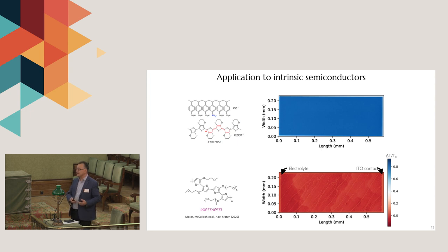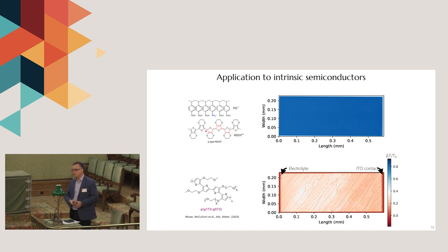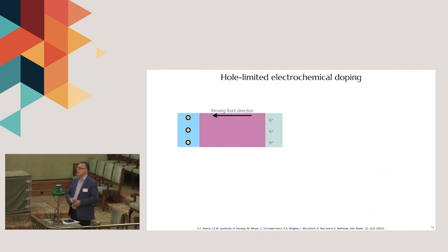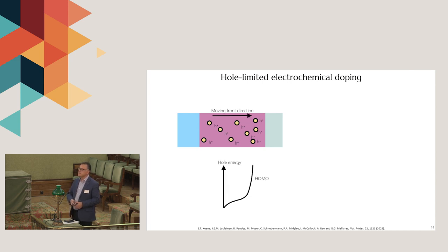This is an undoped polymer that gets doped through injection of anions and holes. And if you see here, the behavior is more complex. You have a front that starts from the left to the right and then reverses direction and goes to the other side. So we can understand this phenomena through looking into the band structure of the polymer. What happens here is it turns out in this case, holes are slower than ionic carriers. So what happens is it's the ions that go in first in the material and start pulling holes towards filling the sample volume. And then when that is achieved up to a certain level, the front reverses direction. So the underlying physics here is that of band filling.